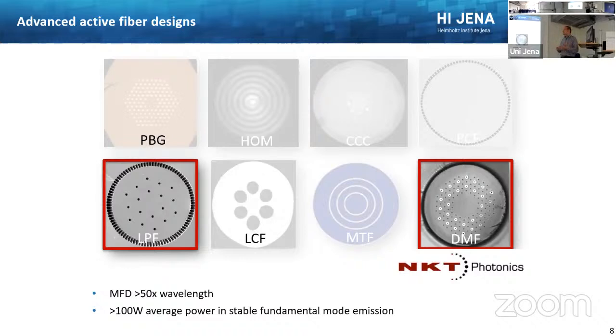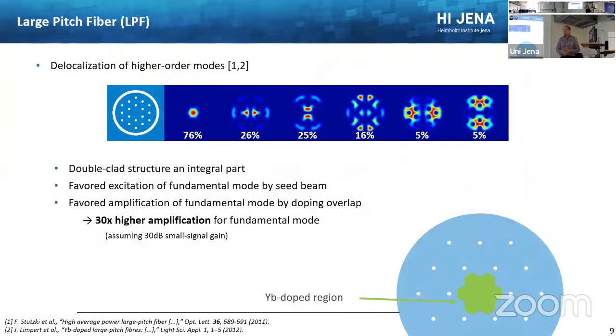And if you use CPA, you can get a couple of 100 microjoules of pulse energies, which is already a useful system for a lot of applications. I just briefly want to talk a bit about how this fiber even works. The working principle is not this simple index step, but it uses what we call delocalization. You can see it in this sketch here, on the left side, the fiber itself with these air holes.